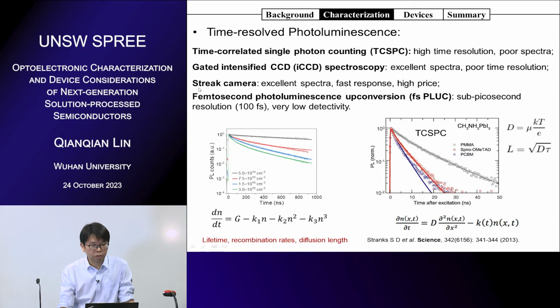Then we can also have a streak camera. You will get much faster than the ICCD. You also get the spectra, but it's more expensive. If you want to look at a very short time region, then you can go to femtosecond photoluminescence upconversion. With the femtosecond PL upconversion, one can get the PL lifetime in the femtosecond or picosecond region. So with all these techniques, what we get is the time-resolved PL.